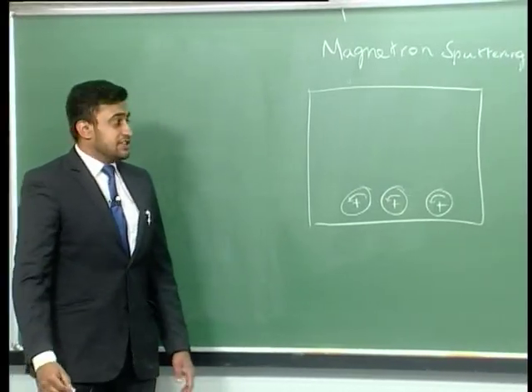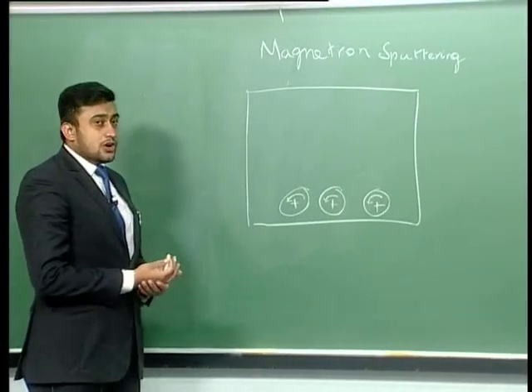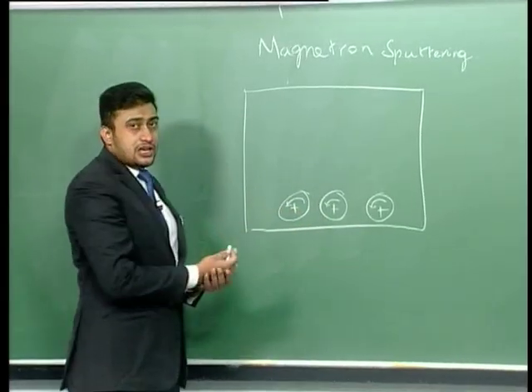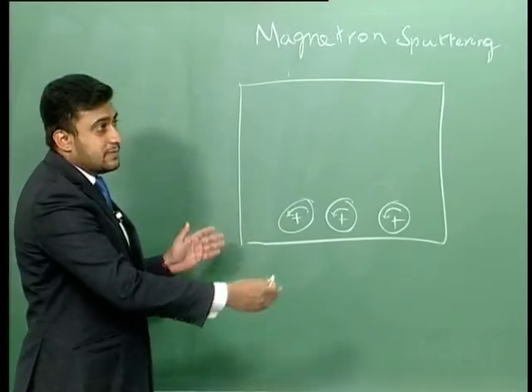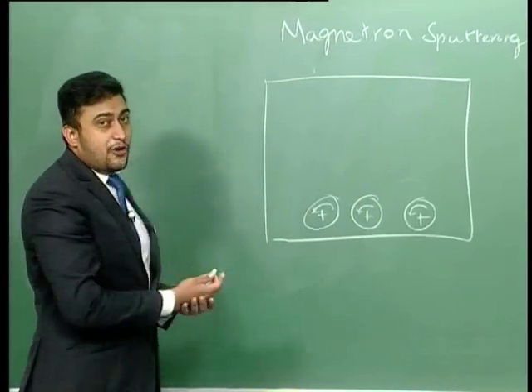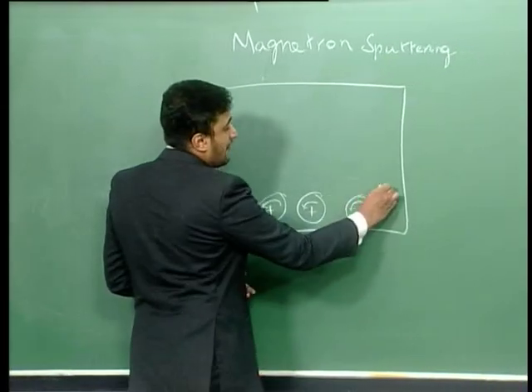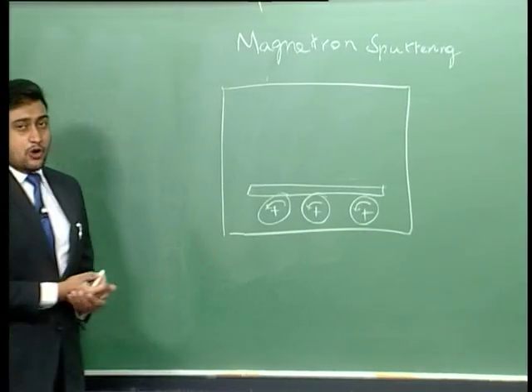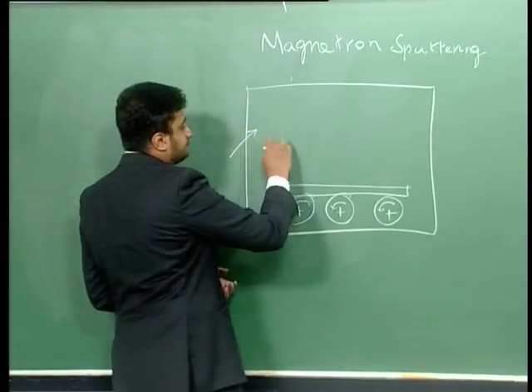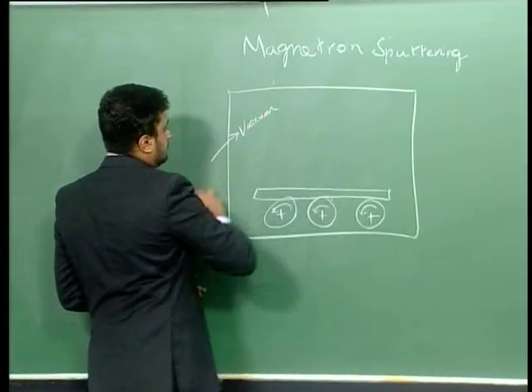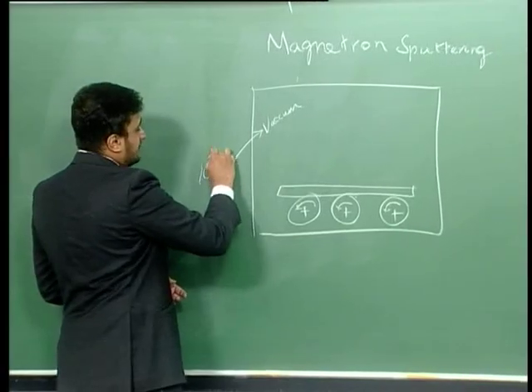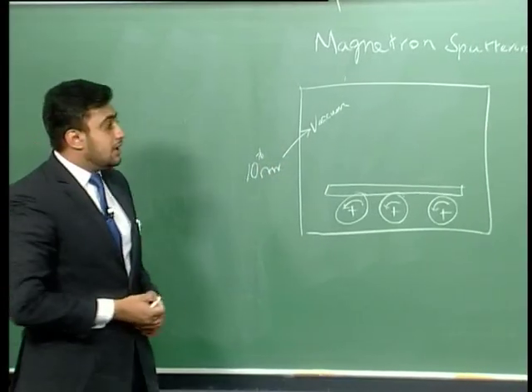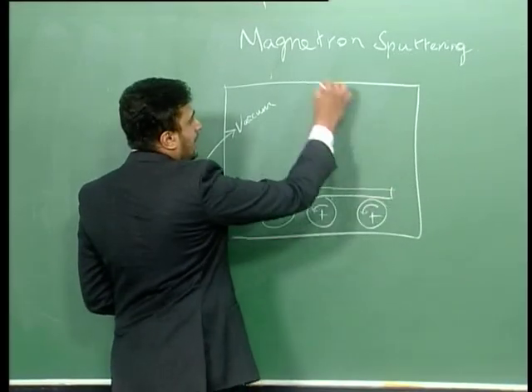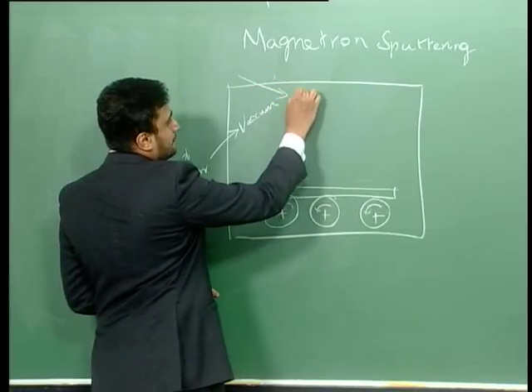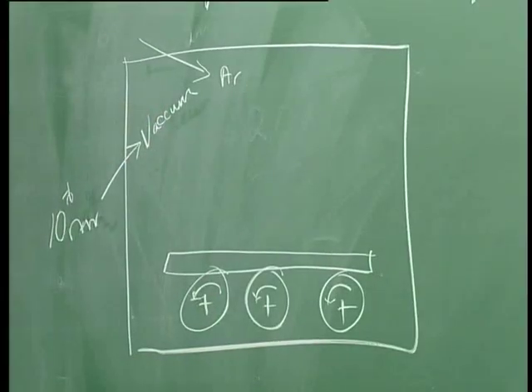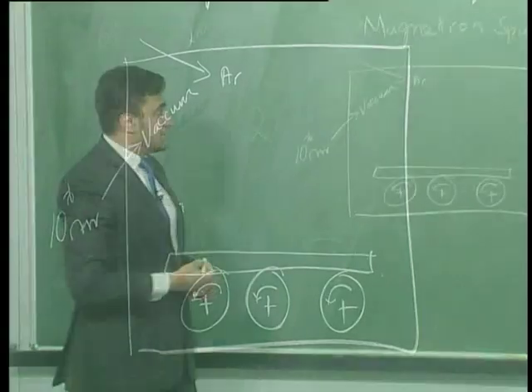The magnetron sputtering process. Now this is done in a separate chamber called a magnetron coater. This is one such chamber in a magnetron coating line. The number of coating magnetron chambers can be up to 42 or even higher in some cases. Over here, the glass moves over rollers in a very high vacuum environment. The vacuum can be as high as 10 to the power minus 6 torr. After this, a process gas is introduced within the chamber. Argon is the most commonly used gas because of its high mass density.